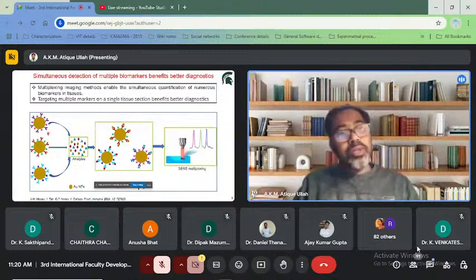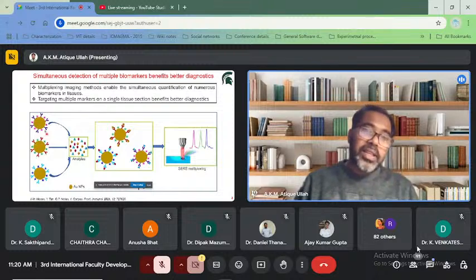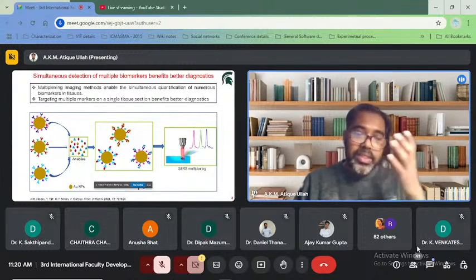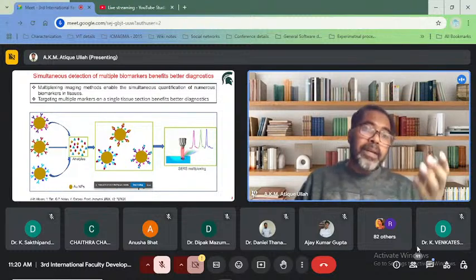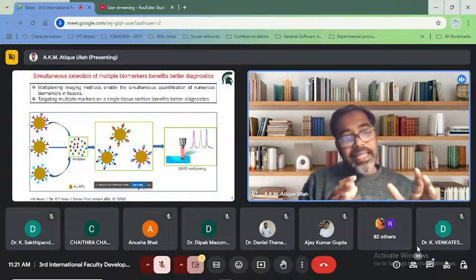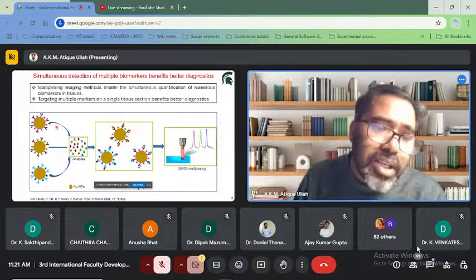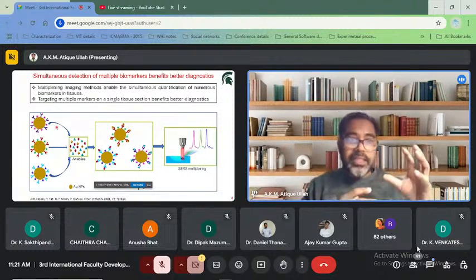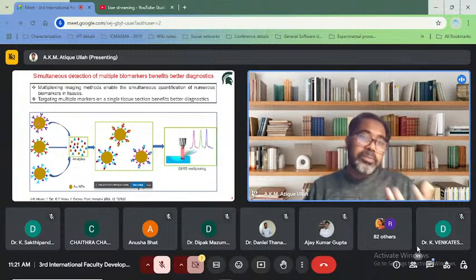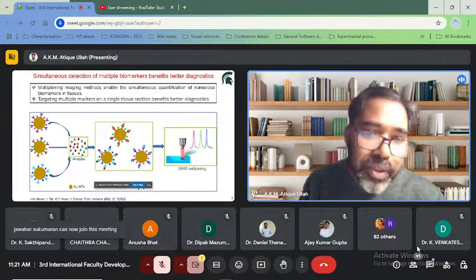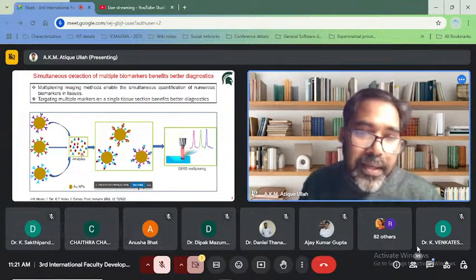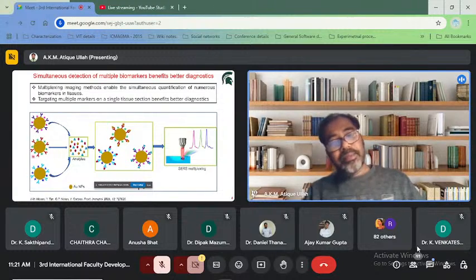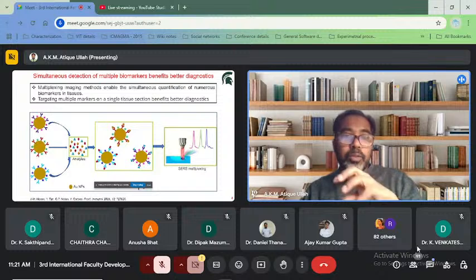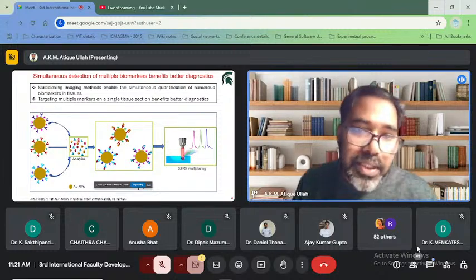So the gold nanoparticle is first functionalized with the SERS active molecule, which is now termed the SERS nanoparticle, and the SERS nanoparticle is further functionalized with the ligand. The ligand can target its own analytes. Now suppose we mix 3 different SERS nanoparticles having 3 different reporter molecules and 3 different ligands, and we apply them to a mixture of analytes. Based on the ligand receptor interaction, suppose these are the receptors.